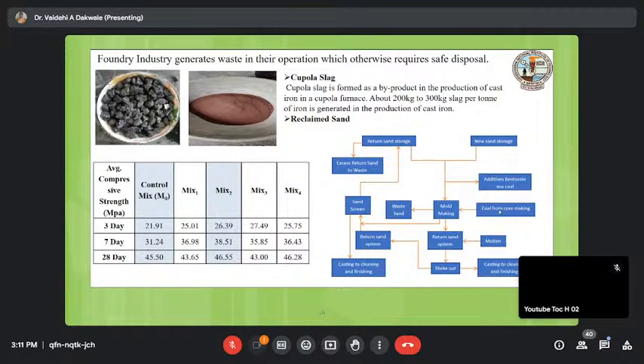Cupola slag we can use at 50% replacement of the natural aggregate, and sand at the same time at 30% replacement of the natural sand. The processing energy required for this material was calculated. For example, sand was available to us from the reclamation plant, so it was used as it was. For cupola slag, we required crushing and sieving, and then used it as a replacement of natural aggregate. Even after that process, we found good saving in cost and in natural aggregate extraction energy, and that is why this becomes a sustainable material.